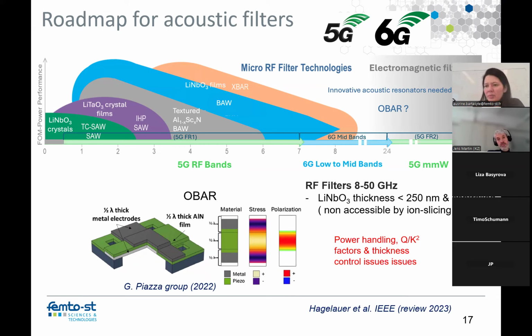And these devices were done mainly on aluminum nitride, but it was limited to 4-point-something gigahertz, 4.5 I think. The films were the limit, because it's very easy to increase the frequency in bulk acoustic wave devices. The frequency is proportional to 1 over the thickness, so you just reduce the thickness and you can go up in frequency. But when you decrease to a very thin film, you cannot reduce the electrode thickness because you still need good conductivity to keep a high quality factor of your resonator. And the mass of the electrodes becomes very important with respect to that of the piezoelectric film. And that kills the electromechanical coupling of the device.